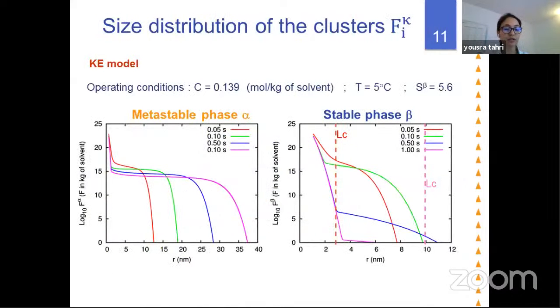So the first interesting results that we got concern the size distribution of the clusters. We did the simulations at 5 degrees, which is a temperature at which the system obeys the Ostwald rule of stages. And here you have the size distribution of the metastable phase clusters and the size distribution of the stable phase clusters. What is striking here and important to see in these graphs concerns the stable phase, because if we see at the time of 0.05 seconds,